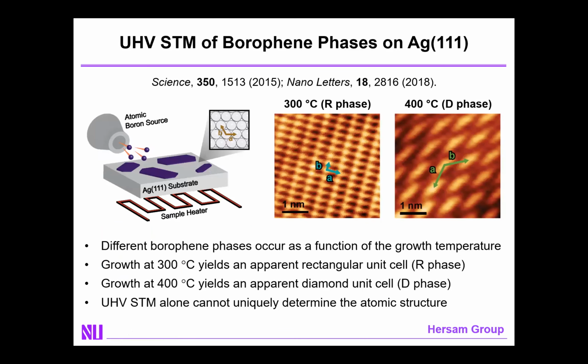And so the way that we ended up getting there was to go to an ultra-high vacuum environment, form an atomically clean and atomically flat silver 111 substrate, and then evaporate atomic boron onto that substrate. And at suitable substrate temperatures, you do form two-dimensional phases of boron. And as you can see in these two STM images, the exact atomic structure you get depends upon the growth conditions. And here's at least two possibilities. One we'll call the R phase because the unit cell appears to be rectangular, and the other the D phase since the unit cell appears to be a diamond-like shape. I will note though that from UHV STM alone, you cannot uniquely determine the atomic structure since you have a convolution of electronic and topographic information in an STM image.